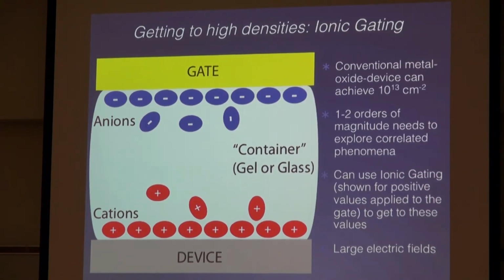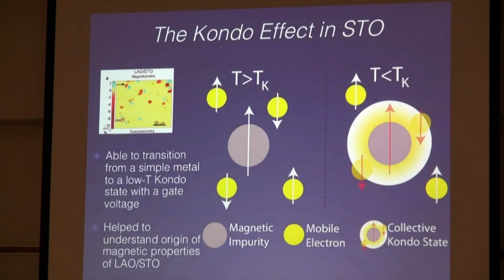And this is really where you gain in ionic gating as compared to conventional gating. You can bring those ions right to the surface so that the electric fields that they generate are very strong. And they're so strong, in fact, if you put too much voltage on this gate, you can actually start ripping out atoms from your device. So we're talking about very, very strong electric fields. As I showed on the previous graph, you can get 1 or 2 orders of magnitude more density swings compared to conventional gating, and you can create very large electric fields. I think both of which will be interesting as we start to look at high density, high spin orbit interaction materials. But for today, we're just going to stick to strontium titanate.